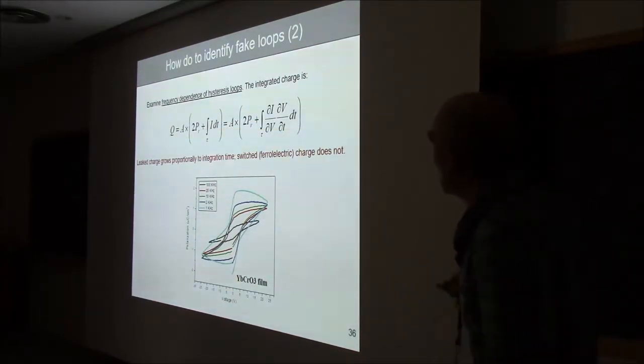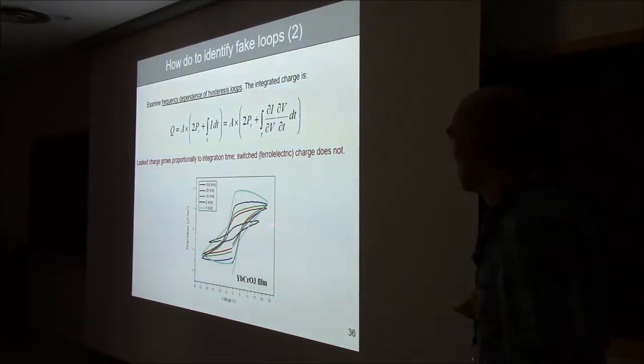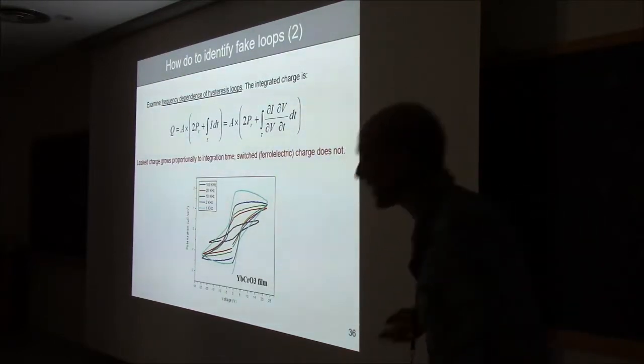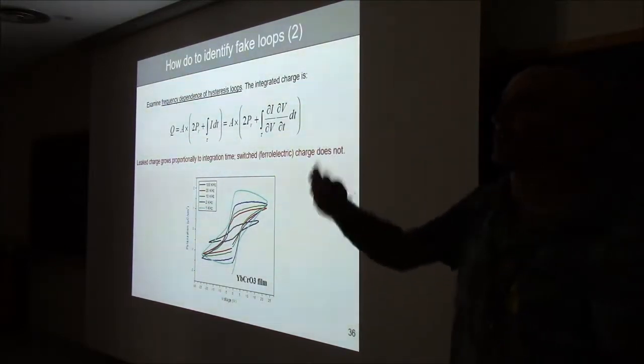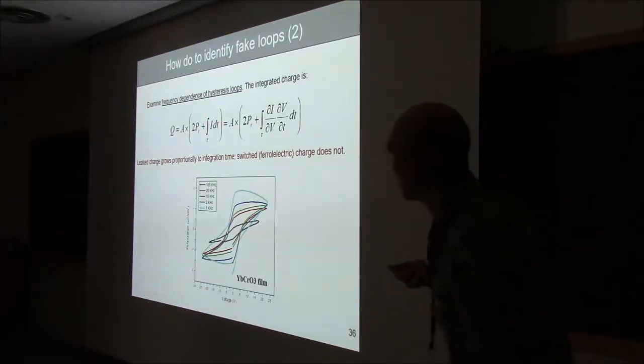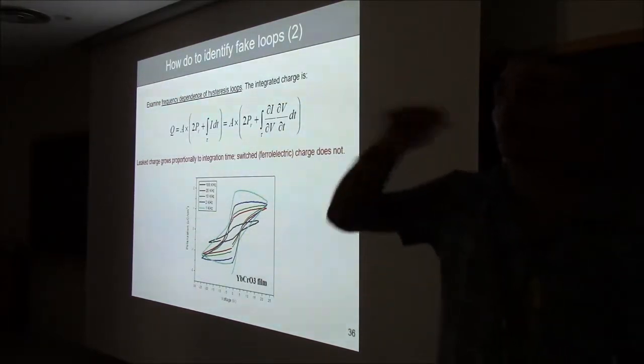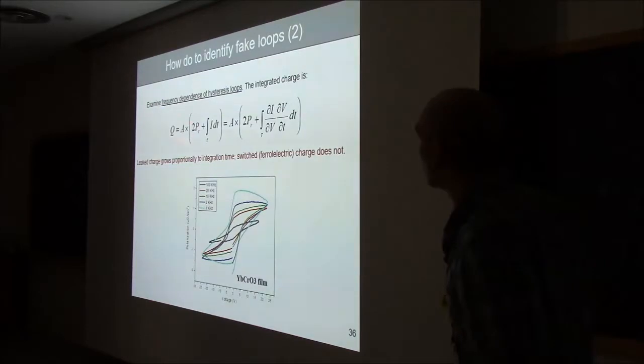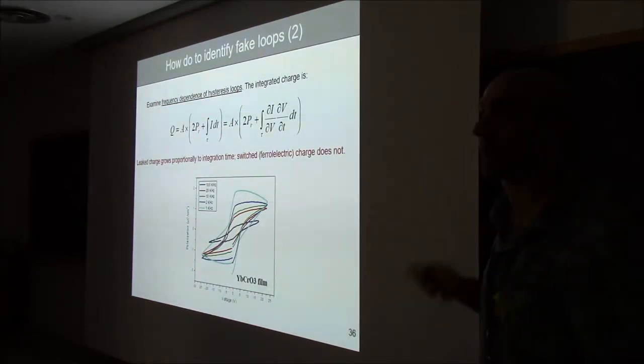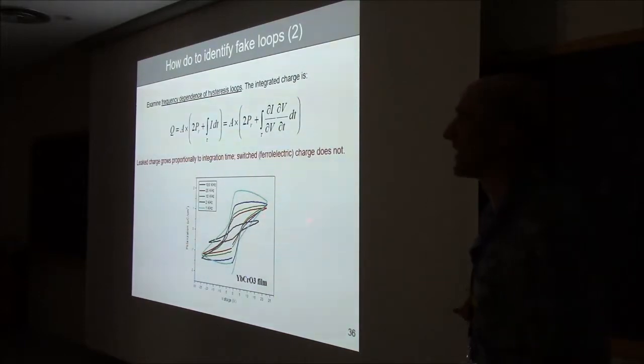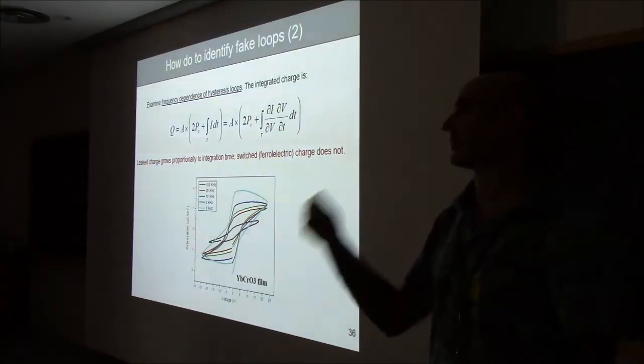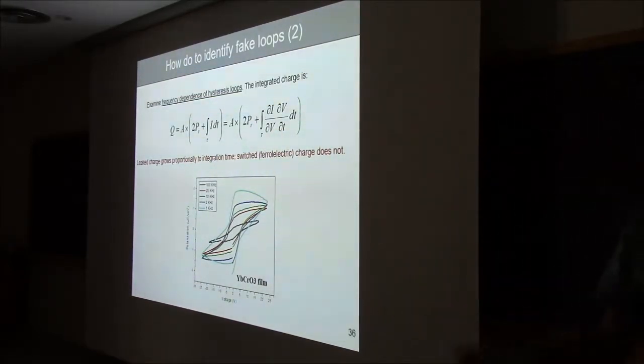So if you measure your loop very slowly, you'll see a very fat hysteresis loop that contains the switching contribution plus the leakage contribution. If you measure very rapidly, you will only have the switching contribution and you'll have much less of the leakage one. Yeah? So if your material is leaky, try to measure it as quickly as possible. The bottom line. Yeah?